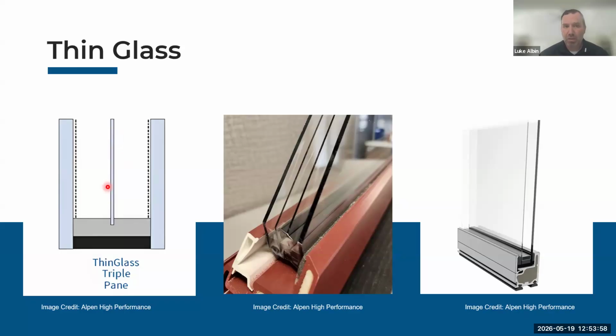The thin glass is actually more flexible than the thicker inner and outer lites, and there is no structural load on it at all. So chances are that's not going to break. The other panes will break first. It still allows for the two low-E coatings on the interior as well. And that can be used for renovations and new windows. What you see here is a triple pane. The triple pane thin glass can be in as small as a 3/4 inch pocket, which is the traditional dual pane system. And then a quad pane can fit in as little as a 1 inch pocket. So a lot of flexibility there.